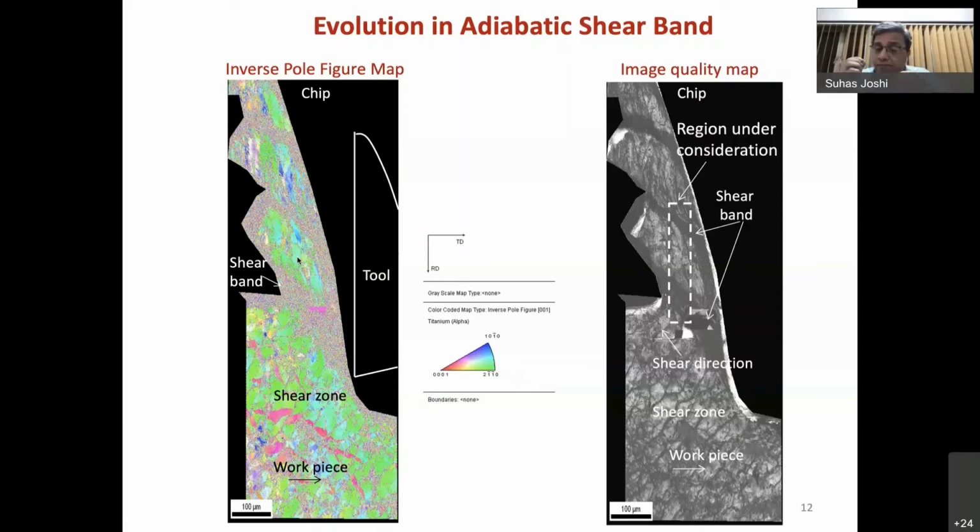So within a fraction of microseconds, this whole segment got formed, and you see the structure here is that there are some intact grains, but around the grains between the two segments, you find that there is very strong crushing of the grains.